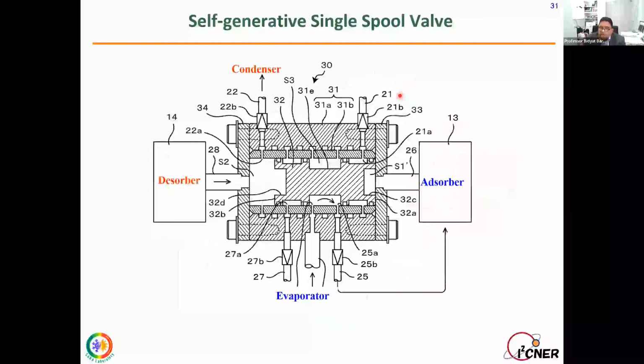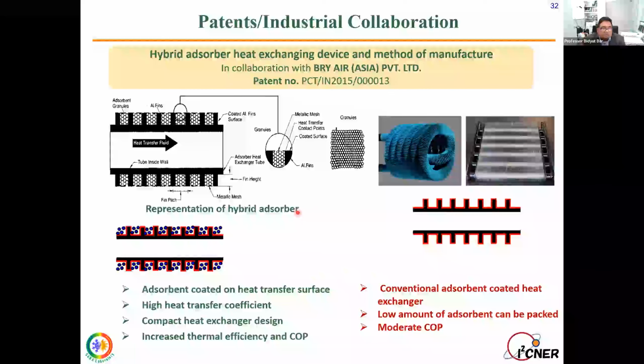In the opposite cycle, when this bed becomes the absorber, pressure is low in this bed and high pressure is in the left side bed. So this vapor pushes our spool so that vapor from this bed through this channel can see the condenser. On the other hand, vapor from the evaporator through this channel can go to the absorber bed. So we get continuous absorption and desorption processes, but we are using only one valve instead of 4 valves here. The valve is very promising. In this case, it is only the size of one A4 paper.